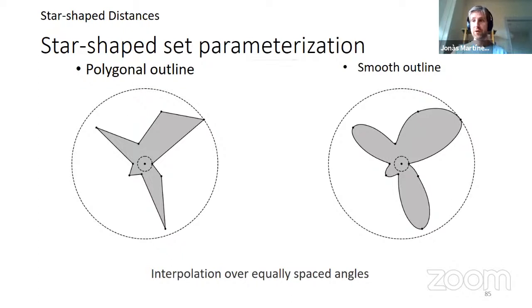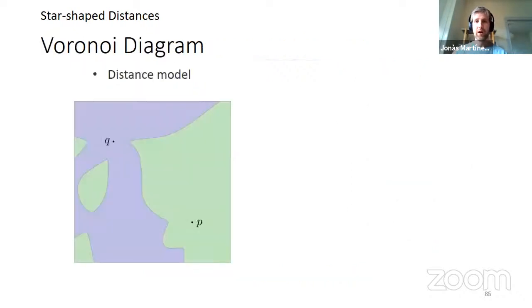So you can do parameterizations with different things. We played with polygonal and smooth outlines, where basically we define different points of this polar function, and then we interpolate between them. And then we stumbled upon the following problem. If you take the Voronoi diagram in a traditional sense, and you compute the Voronoi diagram under this distance, you will get Voronoi cells that are actually made of several connected components. Here you see P, the green region, and there is a green island in the region of Q. And that's actually not good, because since we're interested in the boundary, it will lead to disconnected components of the metamaterial. So what we did is very simple.